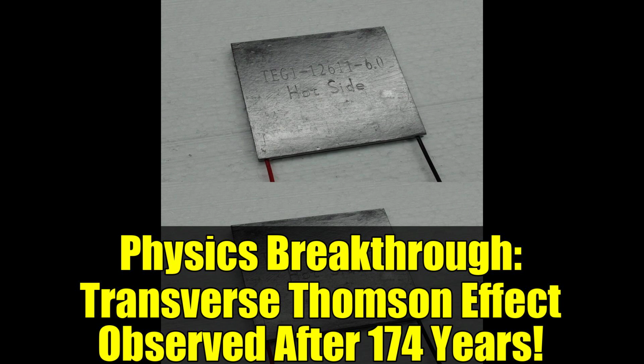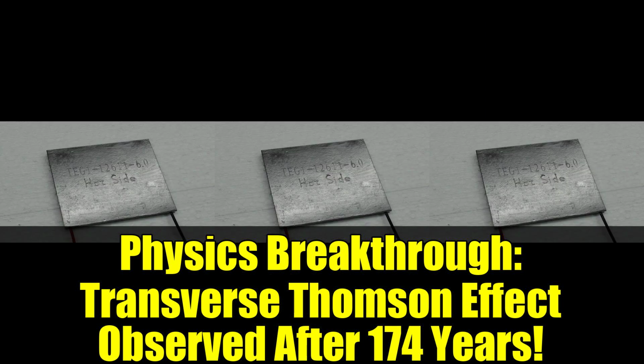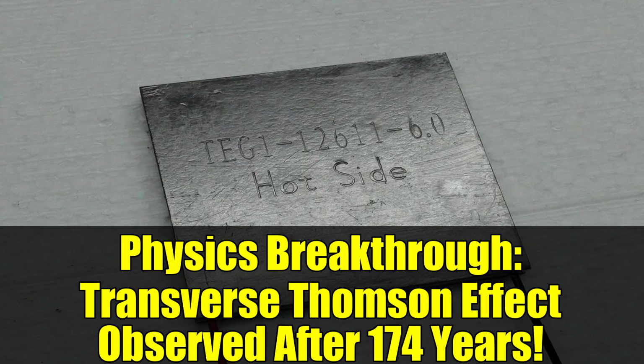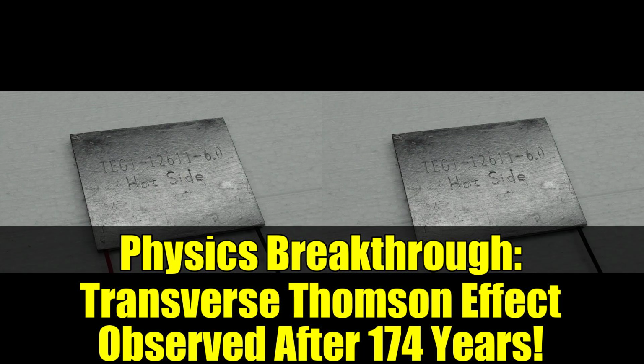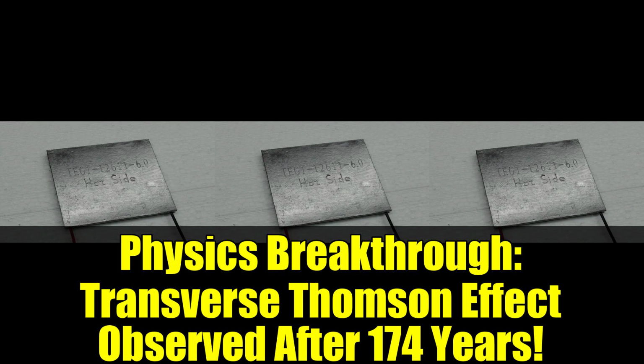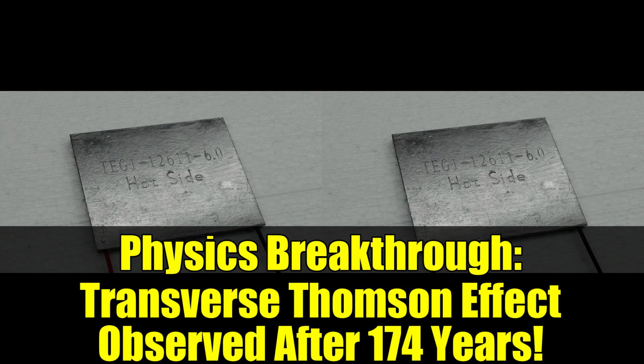temperature. By applying an electric current and a magnetic field at right angles to a sheet of Bi88Sb12, they were able to observe both heating and cooling effects. This specific material was particularly well suited for achieving the desired outcomes. Instead of applying heat to the ends of the material, they directed it to the sides while the magnetic field was applied from above.